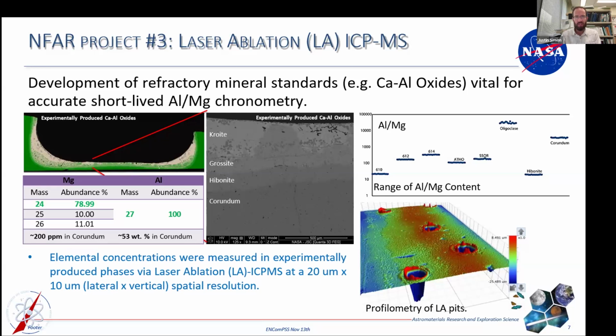This is the excimer laser that we have coupled to our ICP-MS. This was a developmental project that was seeking to establish accurate aluminum-magnesium chronology for the early solar system. The problem here is that we want to make measurements by ion probe or laser ablation multi-collector ICP-MS, but we don't have the standards and the calibrated compositions that we need. This is typically done with the electron probe. But when some phases have very different amounts of the parent and daughter, that is, aluminum versus magnesium in this case, it's hard to do with the electron probe because it just doesn't have the sensitivity for the magnesium.